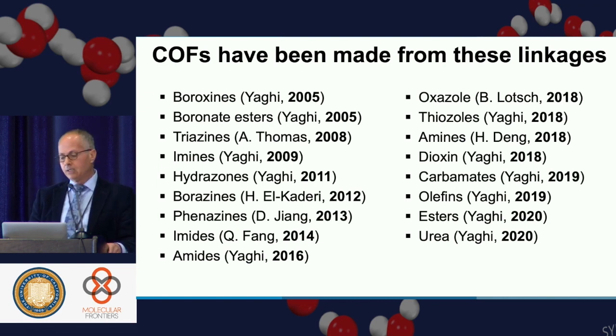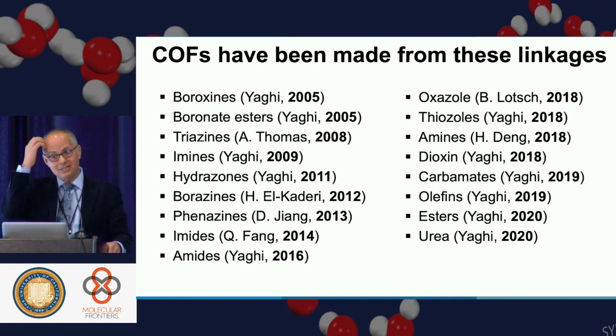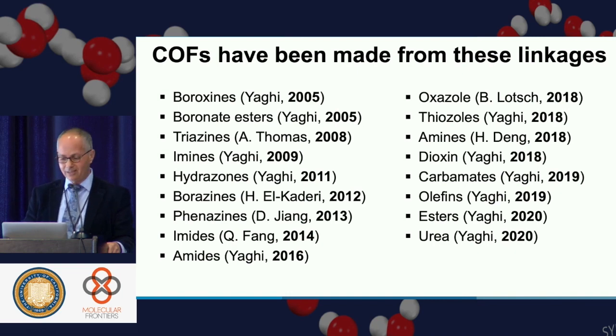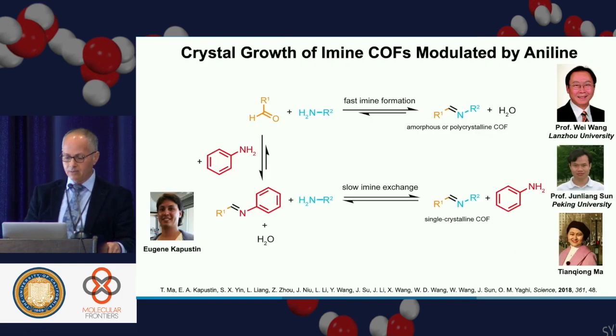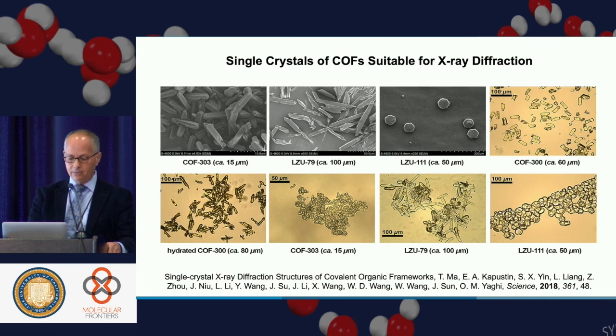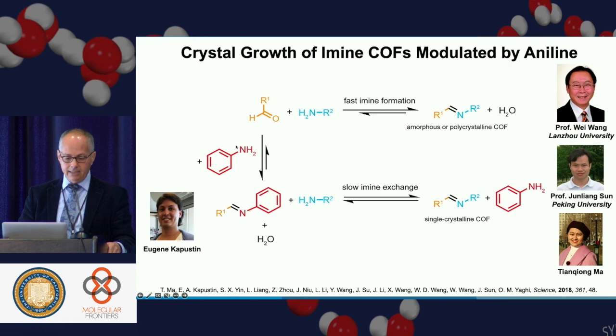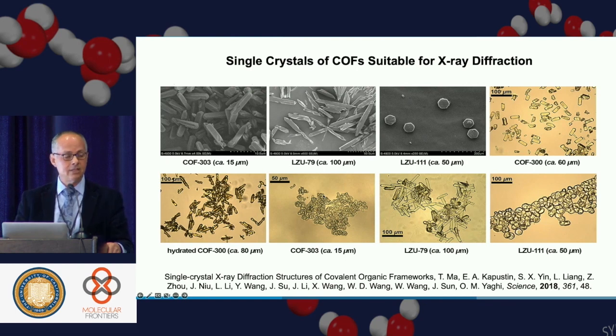Okay? The ultimate thing for me is to show that, in fact, these extended structures could be made as single crystals so that you can do single crystal X-ray diffraction, which is what organic chemists use to characterize their compounds. And there we have been successful, as you see here, by adding aniline to compete in this imine reaction, slowing down the imine exchange in the COF synthesis, you can control the nucleation and make very large crystals that are amenable to single crystal X-ray diffraction.